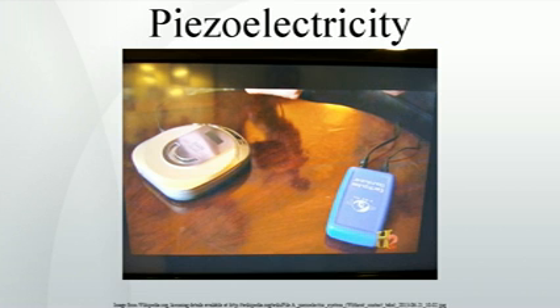Organic nanostructures. A strong shear piezoelectric activity was observed in self-assembled diphenylalanine peptide nanotubes, PNTs, indicating electric polarization directed along the tube axis. Comparison with LiNbO3 and lateral signal calibration yields sufficiently high effective piezoelectric coefficient values of at least 60 pm/V, shear response, for tubes of 200 nanometers in diameter. PNTs demonstrate linear deformation without irreversible degradation in a broad range of driving voltages.